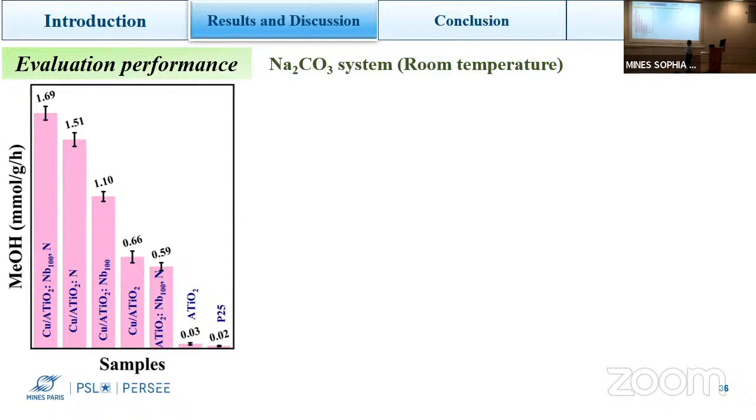So that's why it exists as a co-catalyst. Some of the reaction happens on the copper oxide particle surface, and some on the TiO2 surface. And loading copper can improve the electron transfer efficiency. That's why the catalyst performance gets even higher.